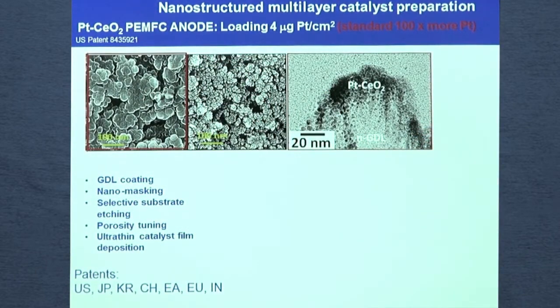And so the process which we are using can be separated into different steps. The first one is GDL coating, nanomasking, selective substrate etching, porosity tuning, and ultra-thin catalyst film deposition. This process is patented. It's covered by 6 international patents.